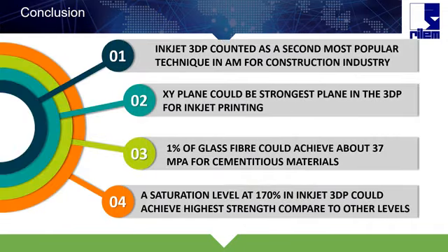At the end, I can conclude the remarkable points of this printing technology. I can say inkjet 3D printing is counted as the second most popular technique for the construction industry in terms of additive manufacturing, and it can be seen that the XY plane could be the strongest plane in the orthotropic properties for inkjet printing. 1% glass fiber could be useful, giving a good result of about 37 megapascal. A saturation of 170 in inkjet 3D printing could achieve very good and higher strengths compared to the other saturation levels.